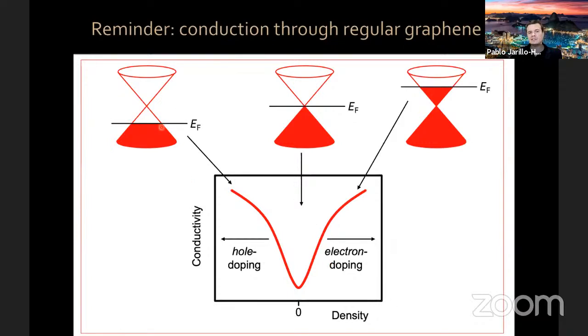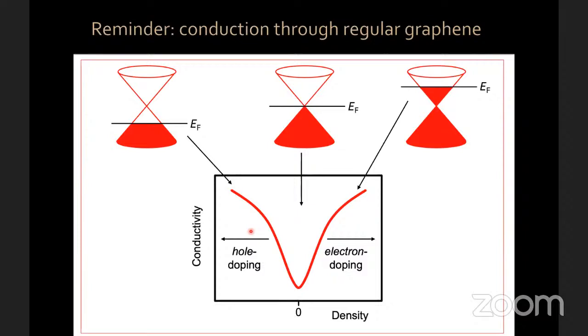If your Fermi energy is deep in the valence band, you have lots of holes, and therefore a very high conductivity. If your Fermi energy is deep in the conduction band, you have lots of electrons, and you also have very high conductivity. If your Fermi energy is at the charge neutrality point, you have very few charge carriers and low conductivity. So the conductivity of graphene versus gate voltage is this V-shape, and that has been seen by thousands of groups around the world. Let me show you what happens when we go to magic angle twisted bilayer graphene.